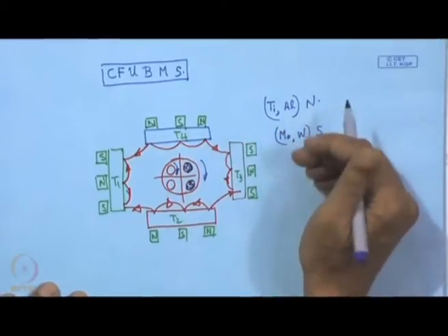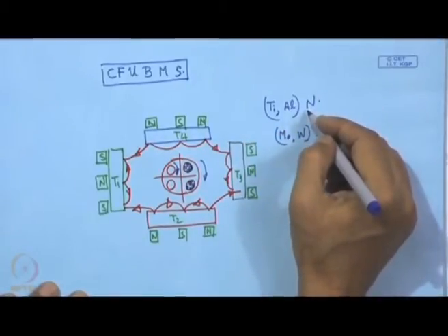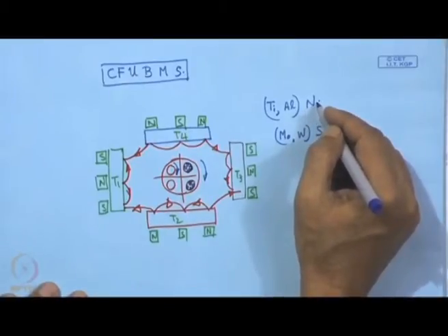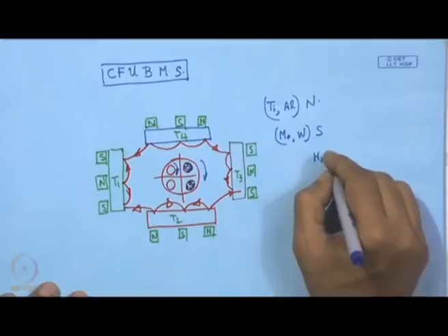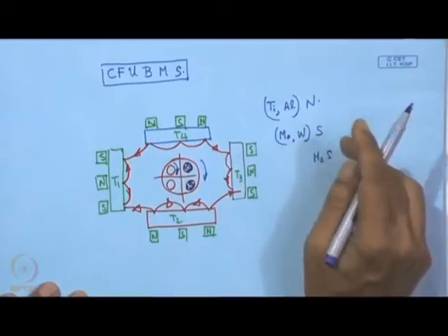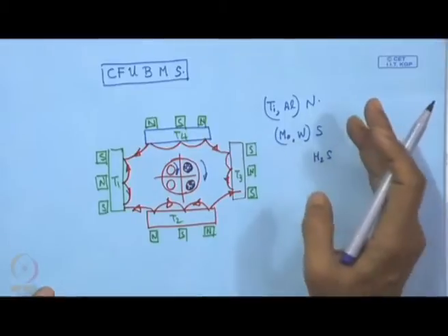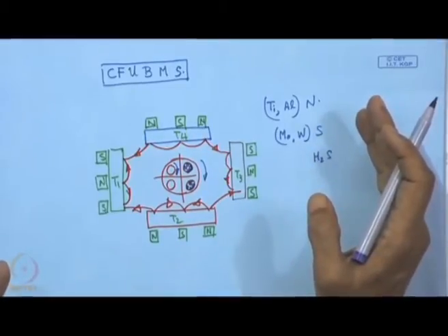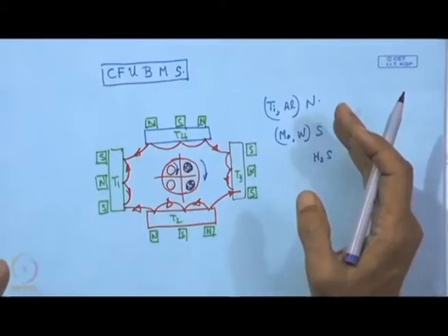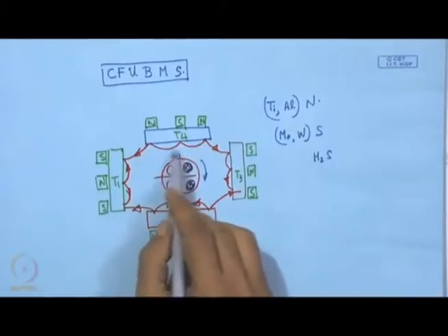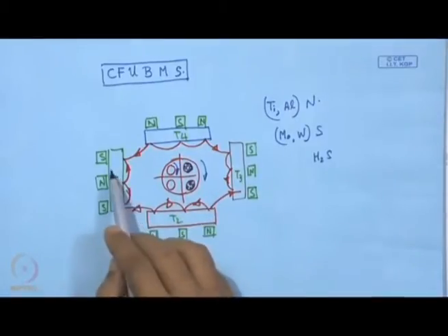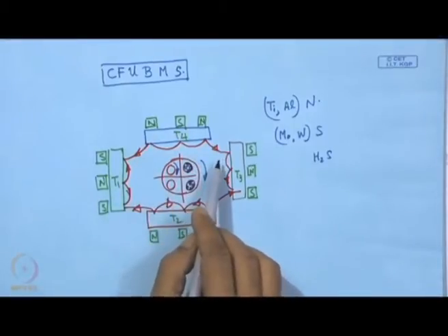and through this reactive sputtering, which we have already mentioned, we can have the reactive gas either in the form of nitrogen, and for sulfur we can have H2S. It can be any carbide, any compound of some of the strategic elements, and they can be mixed here just by coupling these targets magnetically. And here the most important thing is that